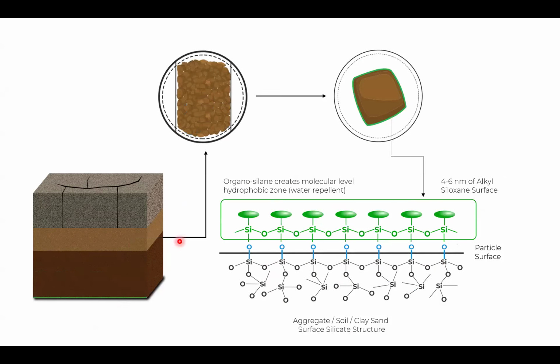So due to this, there is a continuous absorption of water that leads to a reduction in the modulus. Now, once we treat it with the organosilane additives, what it does is create a hydrophobic, water repellent zone. The thickness of such a layer is almost 4 to 6 nanometers, and this is an alkyl siloxane surface that gets formed above the soil surfaces. So essentially, this reflects in the water repellency, and whatever the capillary action or the water infiltration that was happening gets reduced. This reduces the water ingress into the pavement layer, which can reflect in the retained modulus value even under wet conditions.